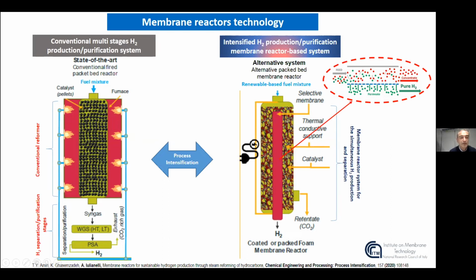In particular, on the left, the conventional multi-stage process, and the natural gas is fed with steam in a conventional reformer operated at high temperature and high pressure, 700 to 900 degrees Celsius, and pressure higher than 20 bar. The reformer stream, or the syngas stream rich in hydrogen, comes out from this reformer, and it needs to be further treated in order to separate and purify the hydrogen present inside. So 2 water gas shift reactors, in particular high temperature and low temperature shift reactors, allow to convert the carbon monoxide present in this stream into further hydrogen and CO2, and then a pressure swing adsorption stage allows to separate the CO2 from the hydrogen that now is pure.